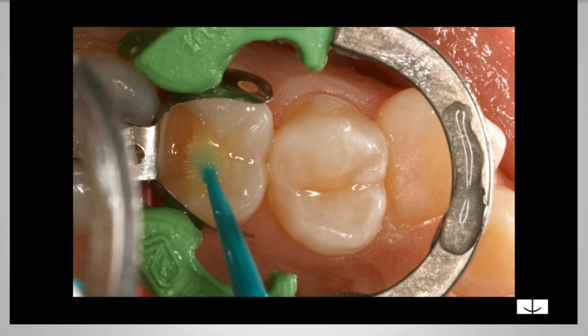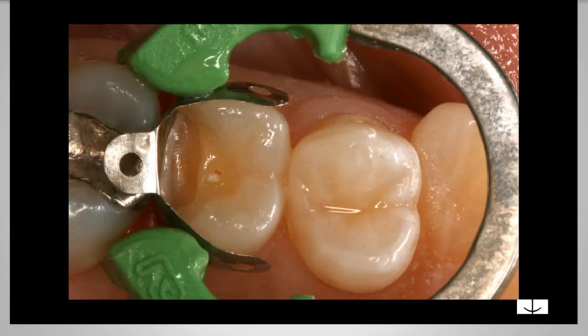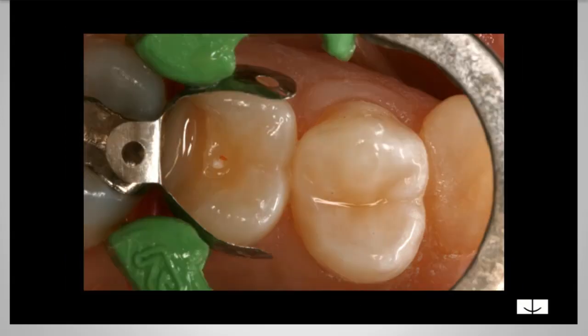So there we go. You like to have that nice glossy finish when you're done, and cure that, and then you're ready to put in your composite. Here I'm using a flowable composite. This is a bulk fill flowable composite. This is SureFil SDR Flow, and you can see it's more translucent, so the light can penetrate deep. You can place this up to 4 millimeter increments.